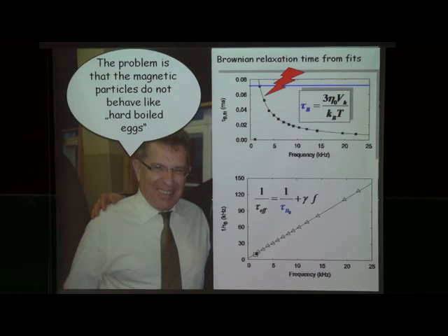So far we have not a complete understanding of this effect, but I would say a rather easy, well, ad hoc explanation for this effect is that you have agglomerates, especially because that was a water-based magnetic liquid, and water-based magnetic liquids are very fond of making agglomerates.